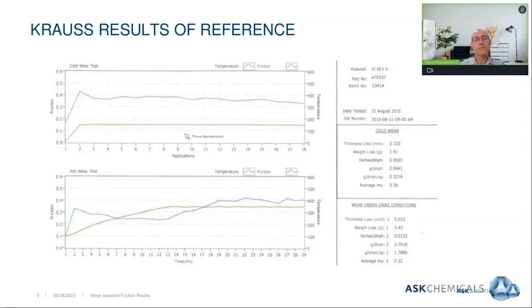What we see here at the 150 degree test condition is an initial slight green fade, and as applications continue further, the fade behavior continues. In other words, a slight reduction in friction coefficient over the number of applications. In the bottom graph, if you follow my pointer, you will see that the test condition was run at 350 degrees Celsius, and the friction coefficient at 350 degrees Celsius shows quite substantial green fade or initial fade, followed by over recovery over time.